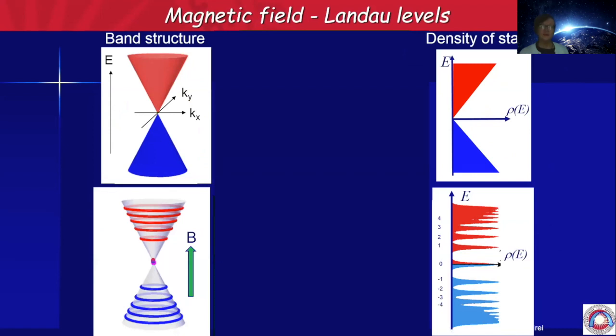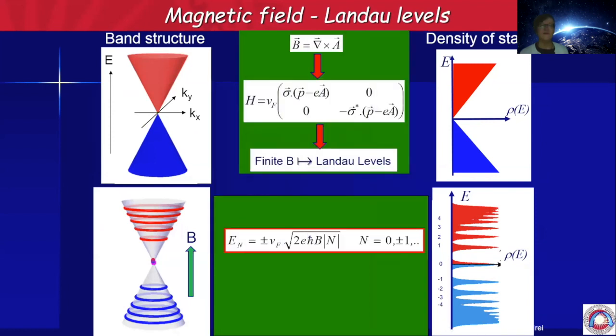Another thing that we can do is apply a magnetic field. What the magnetic field does is break up the band structure into these so-called Landau levels, so the density of states, instead of being this linear dependence, is made up of these peaks corresponding to each Landau level. And the magnetic field is generated by a vector potential, which, in the same Hamiltonian that I showed you before, basically shifts the momentum by an amount of the vector potential here.